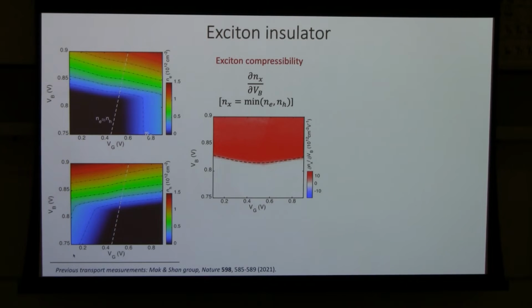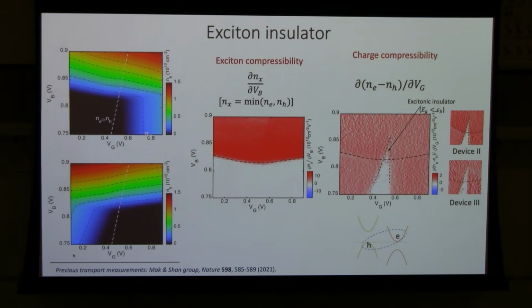But if you have some excess charge, only the smaller number of charge will be able to form the exciton density. So what you can see is in this kind of region, you can have finite exciton compressibility. Basically, you can inject excitons in the system. But at the same time, we can also measure the charge compressibility. That is, when we apply a gate voltage, how much can we inject net charge in the system?